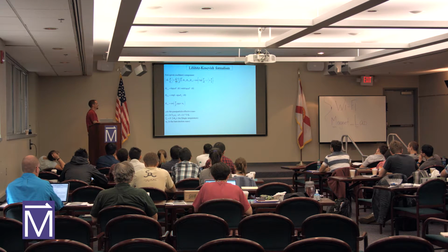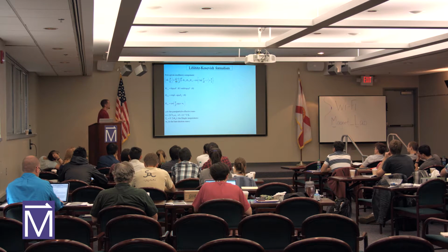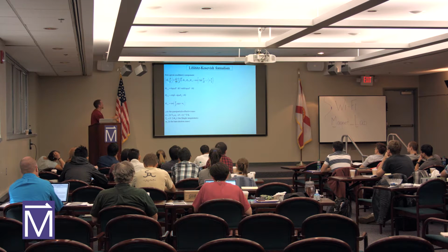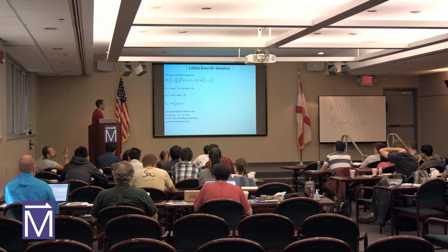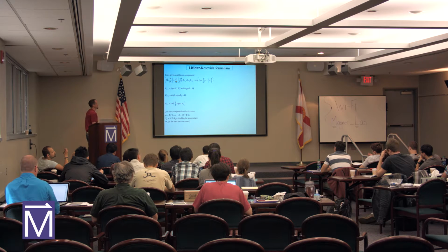Okay, if you've collected a lot of data and you need to figure out what it is actually telling you. Okay, so Lifshitz and Kosevich came up with this formalism to describe the oscillatory data that we get. This can be taken in magnetization data or normalized conductivity. Long formula, but we recognize some parts of it already. This oscillates as a function of inverse magnetic field. Okay, cosine term, inverse magnetic field. And we can learn information from these damping parameters, how the oscillation amplitude changes as a function of different things. For example, this temperature-dependent damping term is written out here.